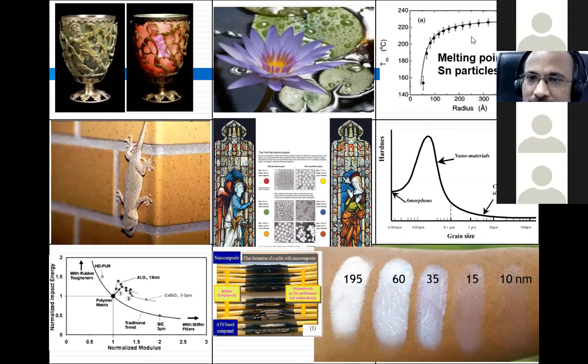Now the question is, when the size is reduced from micrometer to 20 nanometer, which is 200 angstrom, up to 20 or 30 nanometers there is not any significant drop in the melting point. But below 20 nanometers, you can see there is a significant drop in the melting point. When the size of any metallic particle is about 2 to 3 nanometers, you can see that their melting point is close to room temperature.